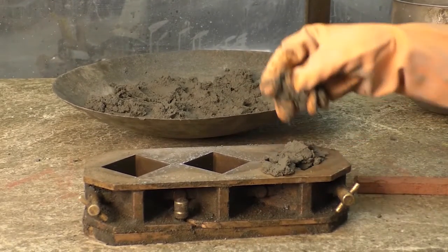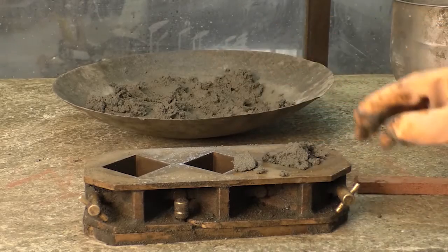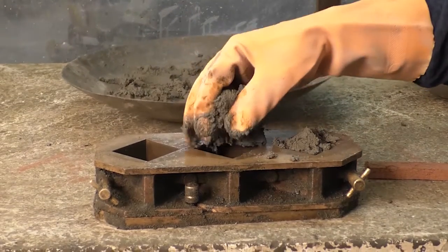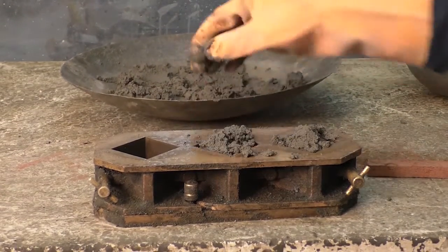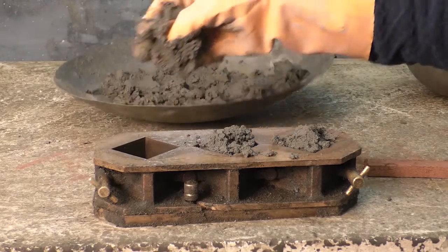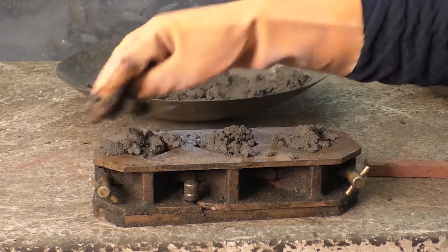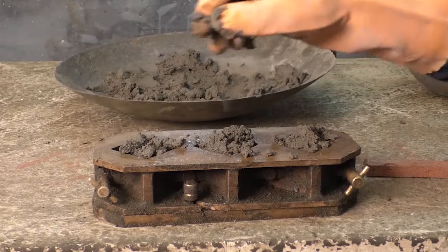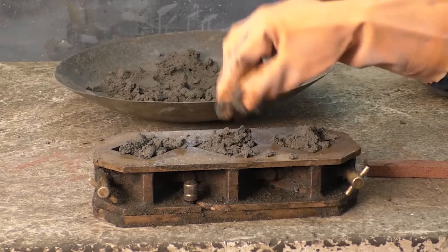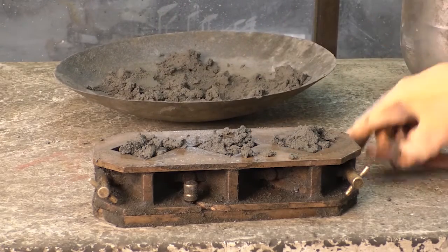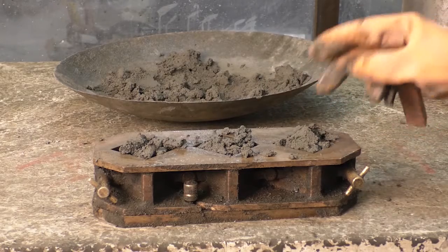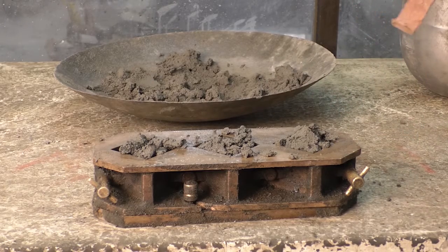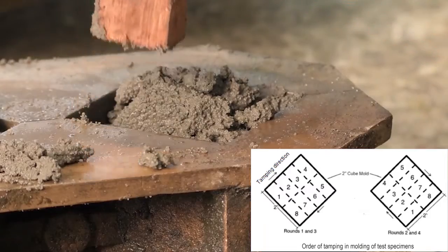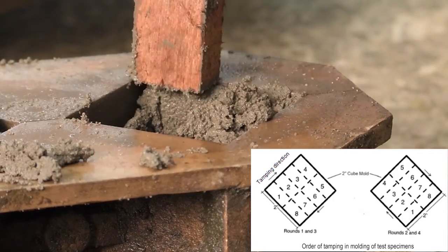We have to place a layer of mortar about 1 inch thick in all of the cube compartments. We have to tamp the mortar with the tamper in each cube compartment 32 times in about 10 seconds in 4 rounds as shown in the video.